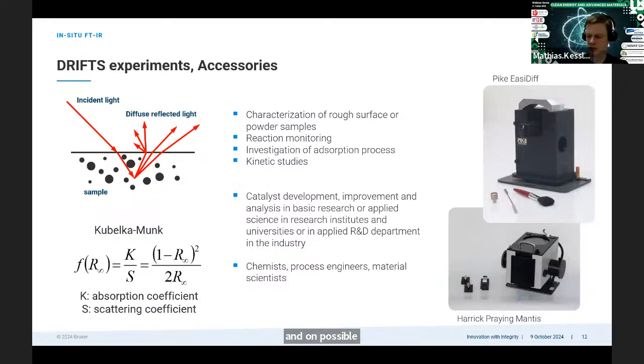What is DRIFT spectroscopy? It's diffuse reflectance infrared spectroscopy. So we have the incident light, which hits our sample, which is a powder usually. And on the powder surface, the beam is not reflected specularly, but instead it's reflected diffusely, so in all directions. And this means we need an optic which is able to collect the diffusely reflected light, and this is usually done with a big spherical mirror.